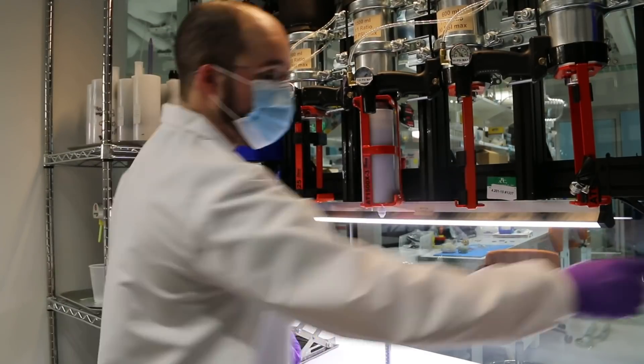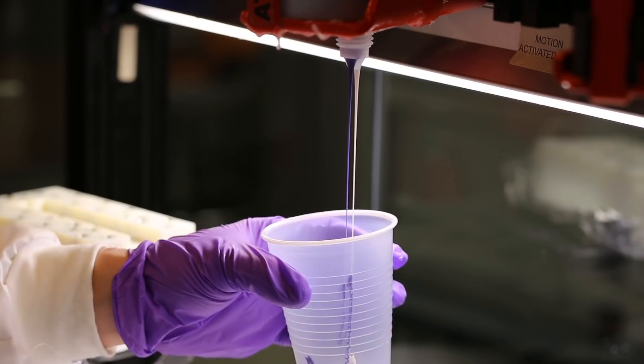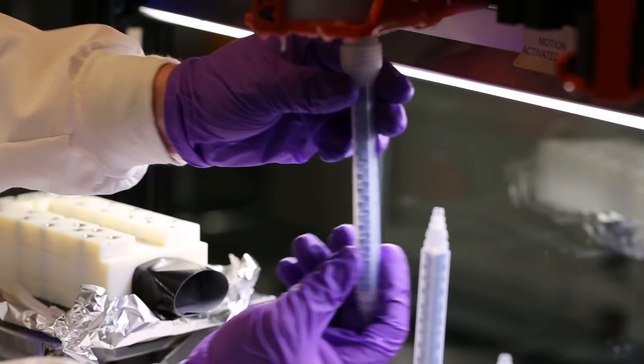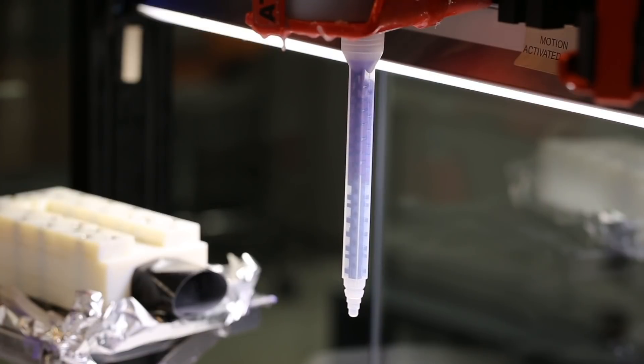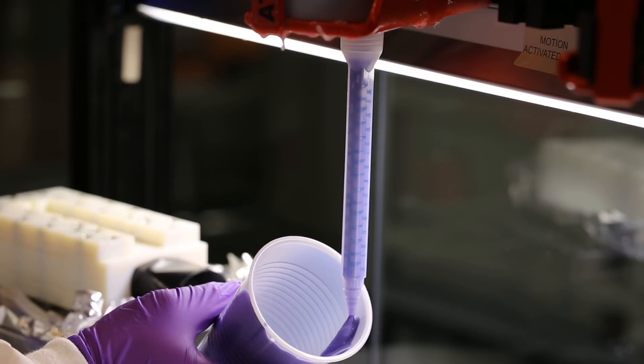We are now ready to injection mold. With a new cartridge, we need to purge both materials until they come out at the same amount. We can then get a static mixing nozzle and attach it to the cartridge, and dispense for a little bit until the material is fully mixed and we see no striations between parts A and B.